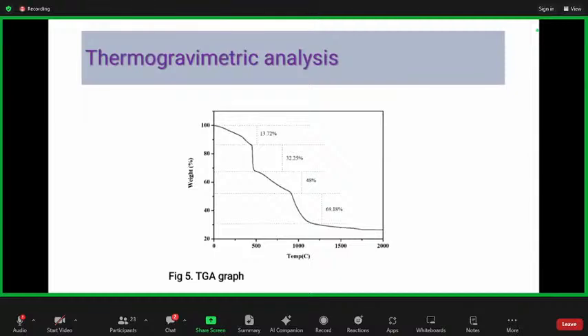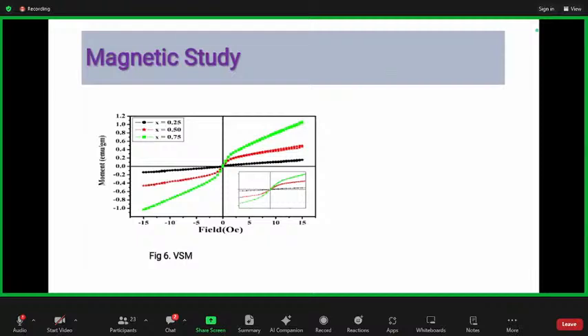The next one is TGA, that is thermogravimetric analysis, which detects the thermal stability of the product. From this graph, it has been shown that the synthesized material is thermally stable at high temperature. Then the magnetic study. As the concentration of the doping element increases, the magnetization of this material decreases.